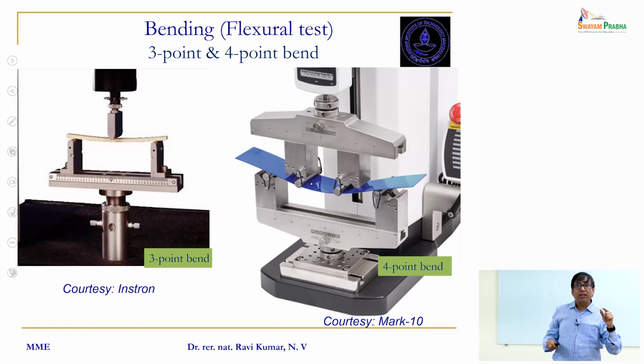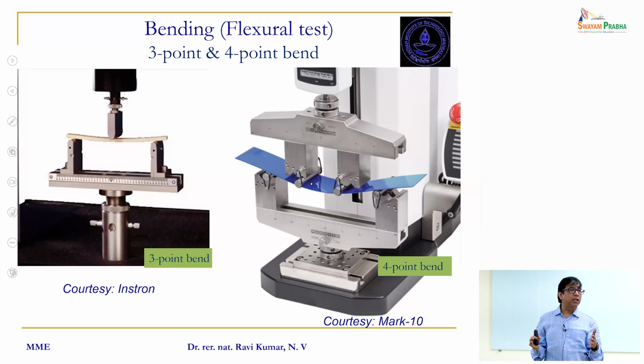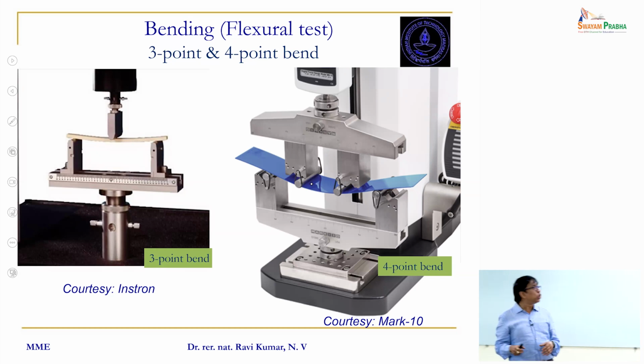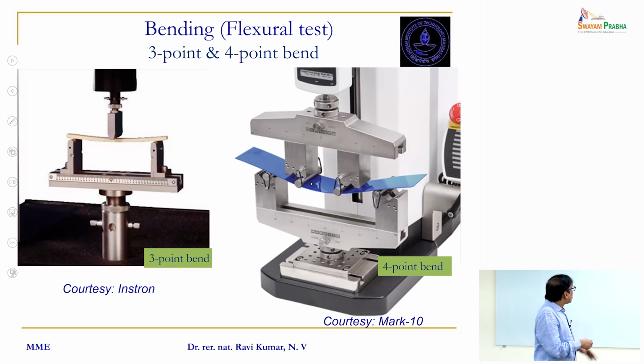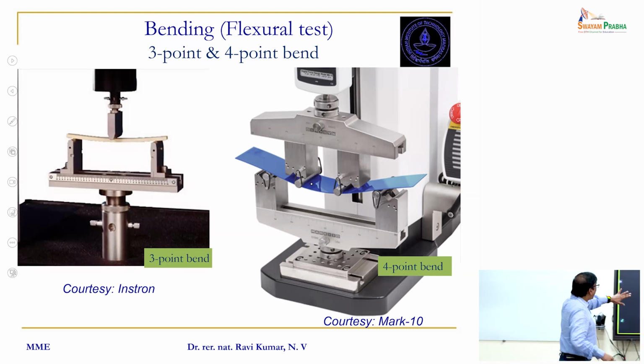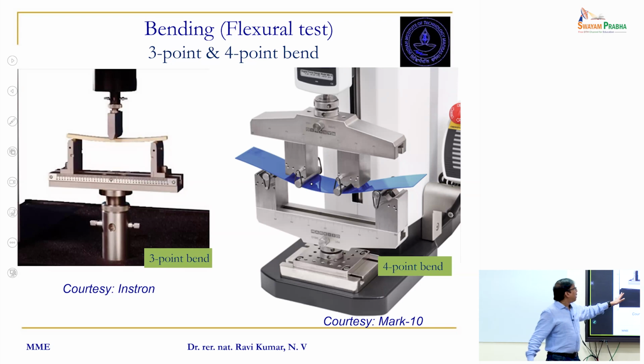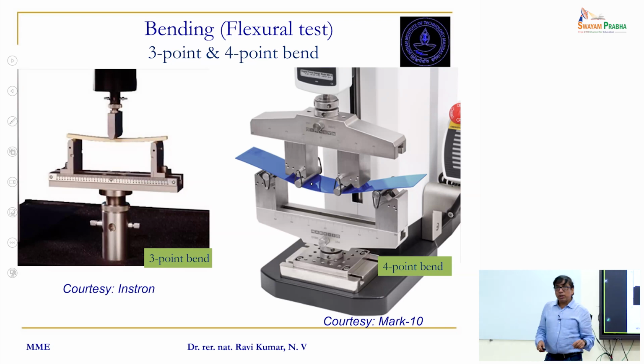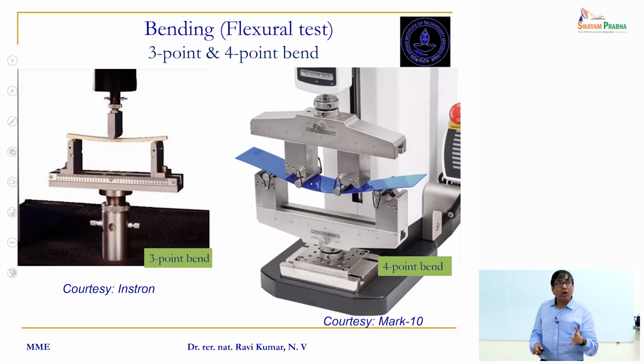If you cannot fabricate your ceramic samples as per ASTM standards, one of the possibly permitted methods would be to simply downscale the same thing. Keep the ratio the same, but downscale it and then do it, if you cannot fabricate bigger size samples as per ASTM standards. So this is a 3-point bend, that's a 4-point bend. I don't know which one you have seen in life, but people use both. But what is actually really correct? What gives you an accurate description of this uniaxial bending strength?